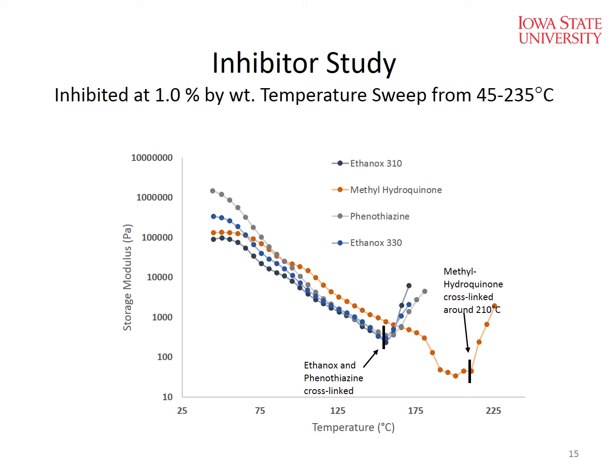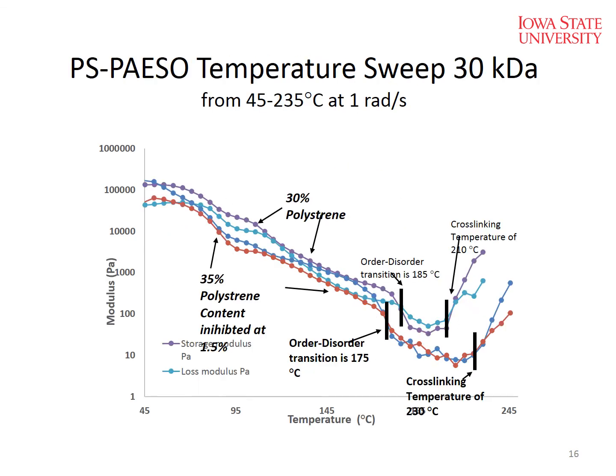And so we've gotten out that way with a methyl hydroquinone. We actually use some other ones we can't really get into a lot of conversation about right now. It stretches that even a little bit further out there. This is a busy graph, but again, this is just highlighting that we can see the cross-linking temperature out towards that 220 mark, and we call the order-disorder transition. And then this highlights the 30 versus 35% polystyrene content, and we're inhibiting at 1.5%.